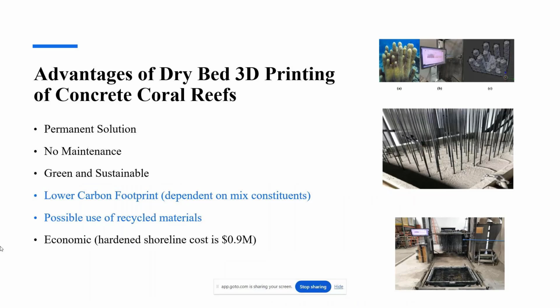So this dry bed 3D printing of concrete coral reefs kind of provides a permanent solution, given that we cannot justify or judge, but the expected lifespan is going to extend way beyond 25 years as compared to 6 to 8 years of nourishment. And during this time, no maintenance will be required. It's sort of green and sustainable, given that we can lower the carbon footprint depending on the reduction of cement or the use of different supplementary cementitious materials in lieu of cement, or using recycled materials.